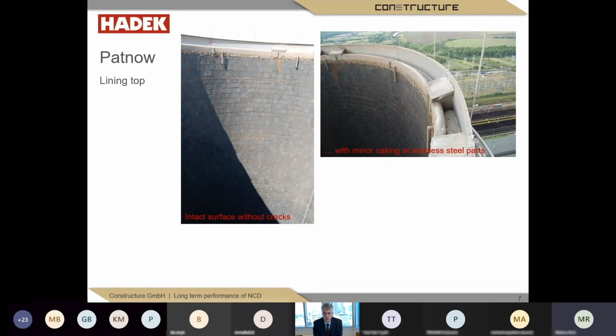What you can see is we have an intact internal surface without cracks and with minor caking at the stainless steel parts, but nearly nothing, no dust on the inside of the lining surface. We have no corrosion on the steel parts, and after 10 years of operation it's quite clean at the very top and without any visual damages.